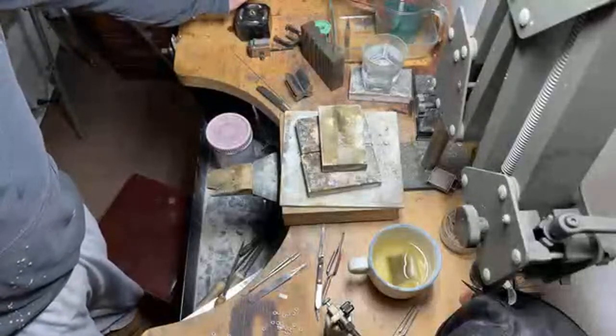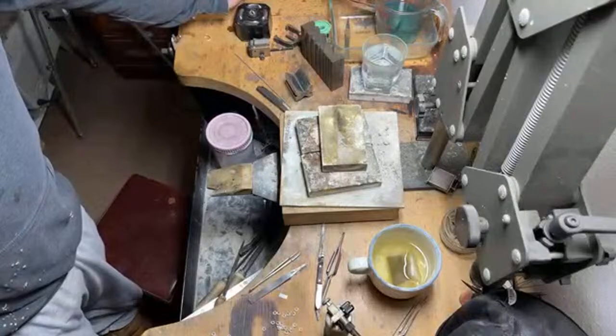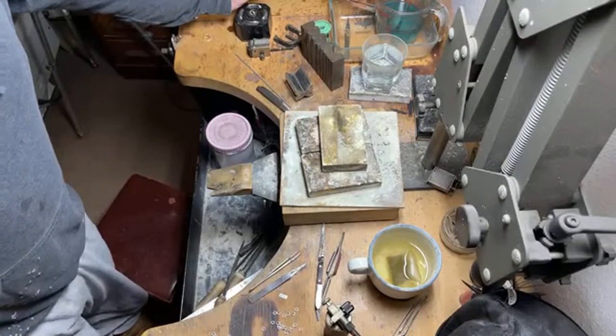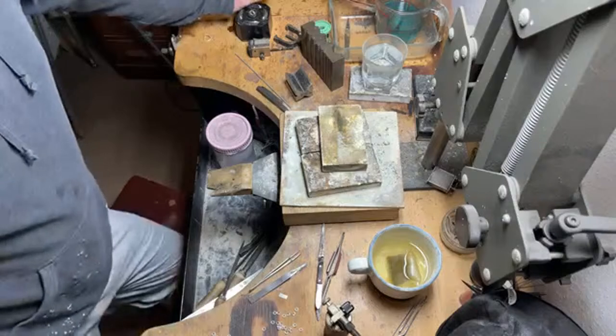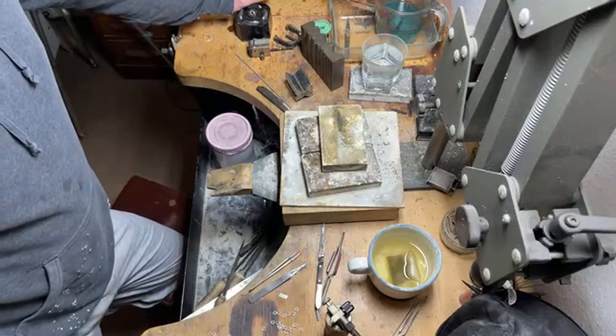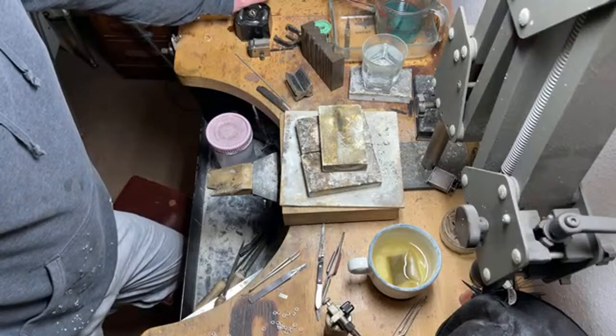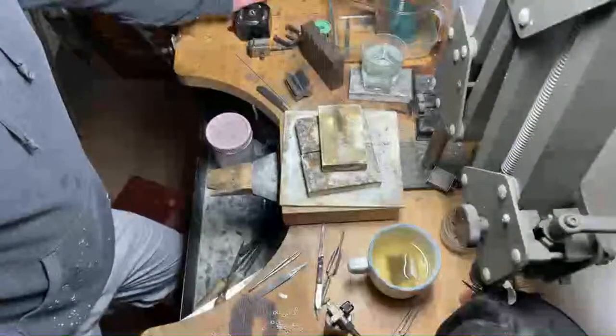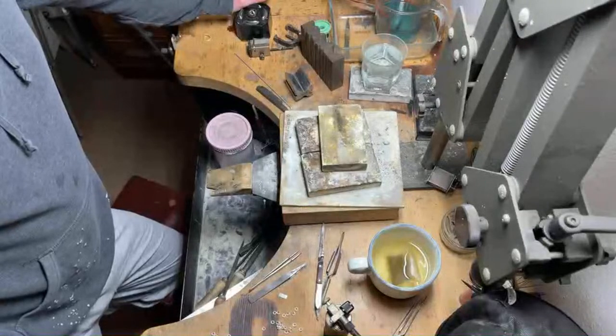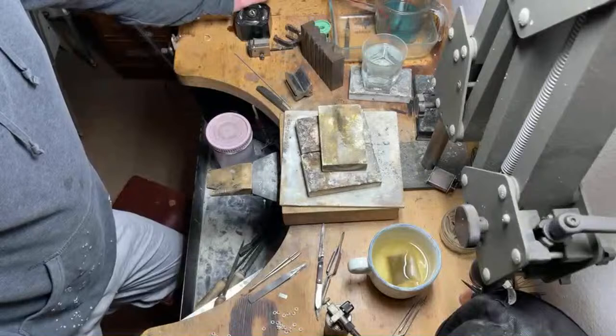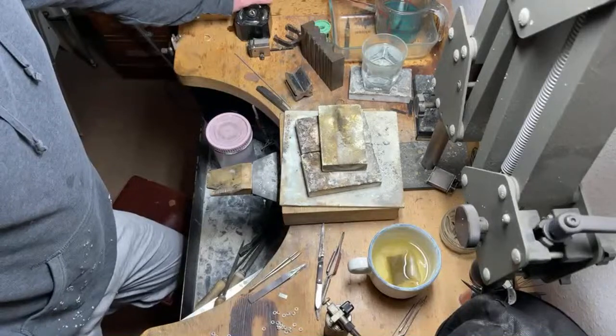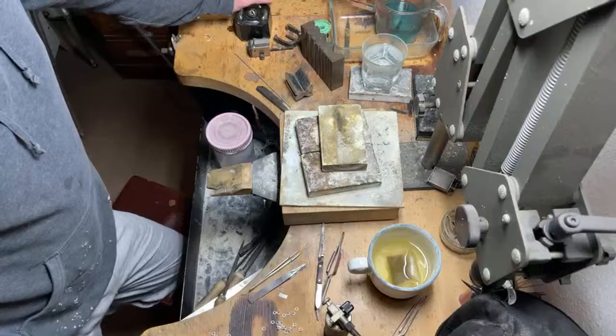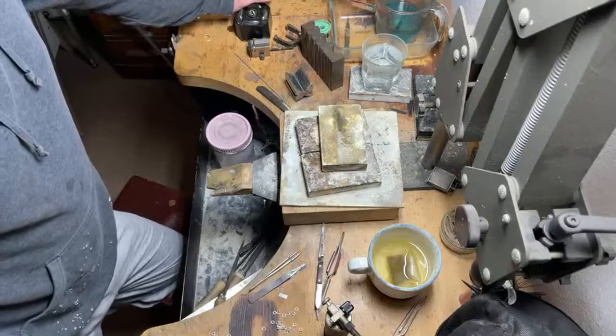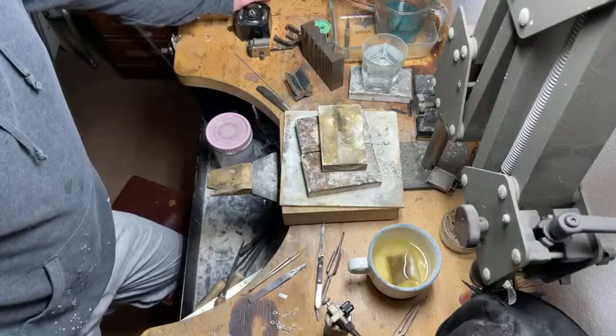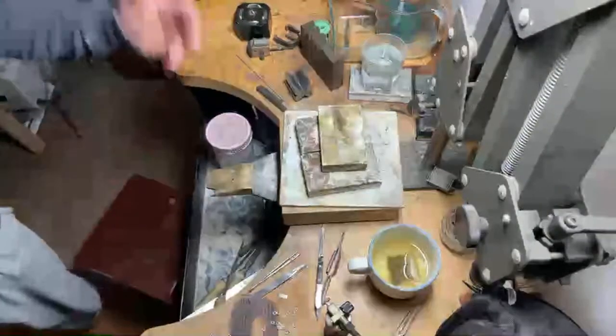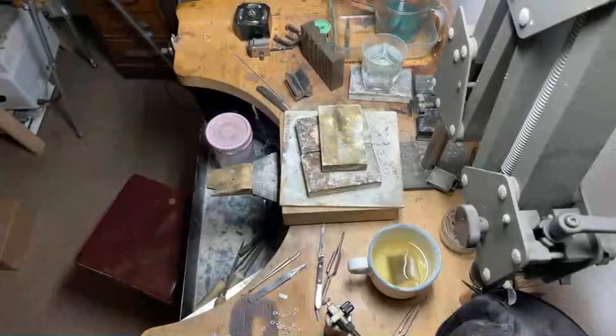So we're going from about 7 or 8 mil. That will go down, on the rolling mill, to about 2 mil. Maybe 1.5, 2 mil. And every about 0.4, 0.5 of a mil, we'll have to anneal it. So you do the maths. And then once we go onto the draw plates, from somewhere between 1.5 and 2 mil down to 1 mil, probably about 2 mil down to 1 mil, it's every 2 or 3 holes. And you're looking at about 0.1, 0.2 of a mil. So that in itself is 5 or 6 probably minimum annealings. So yeah, it's something you just have to constantly do to avoid cracking.